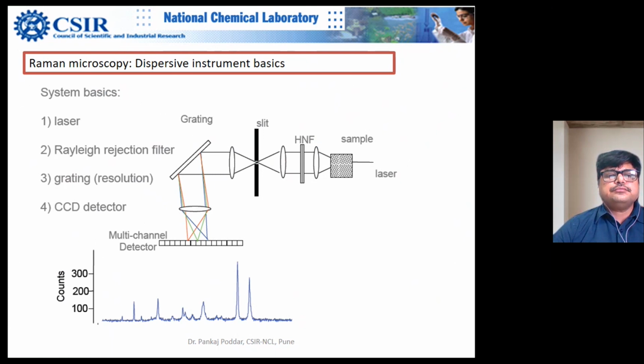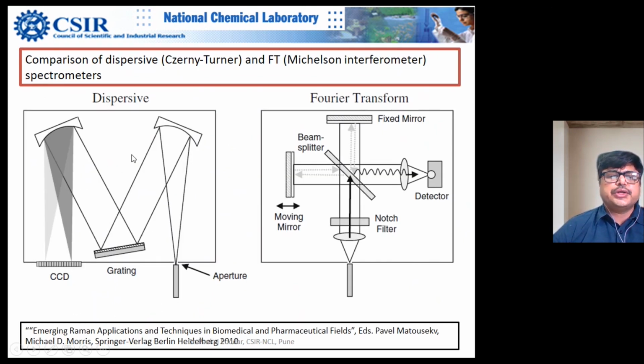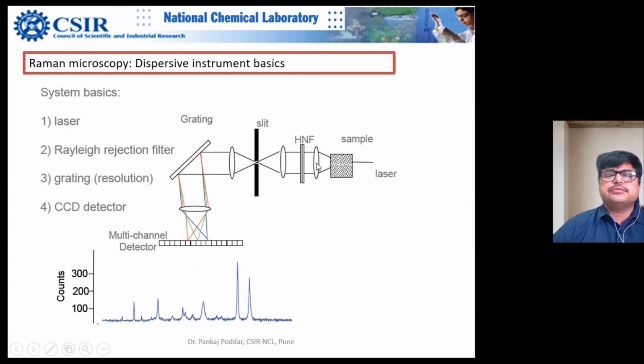Yes, this is also described here. This is a mirror-based system. You see there are no lenses, only mirrors, but you can also have a lens-based system. Using lenses you can also do the focusing and defocusing, but you have the problem of chromatic aberration, because lenses will have different focal lengths for different wavelengths.